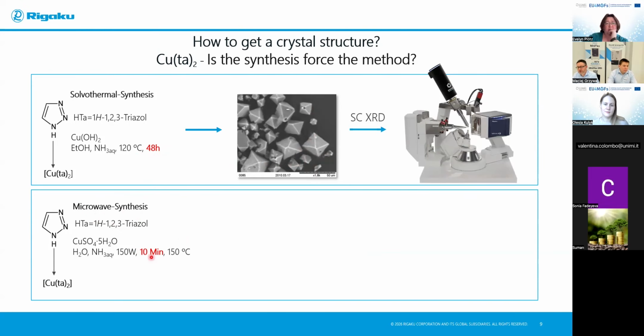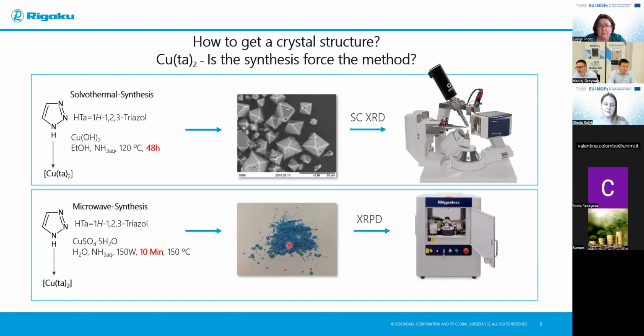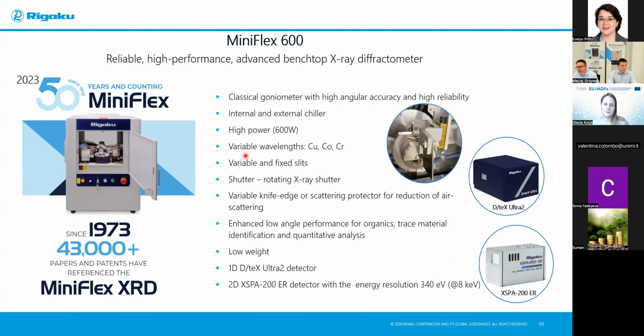To accelerate the reaction, another microwave synthesis reaction was developed that the reaction time was shortened to 10 minutes, always resulting in the product as a very fine precipitate. This raised the question: is it possible to collect the powder data and solve the structure using the data which were collected on the benchtop XRD instrument? And here I'd like to introduce the Miniflex 600 advanced benchtop X-ray diffractometer.